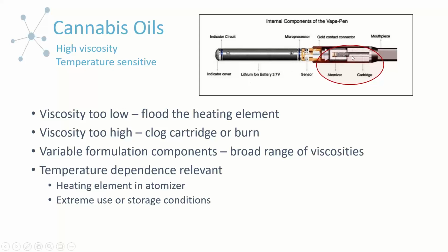Because if the viscosity is too low, then we can have flooding, essentially, of the heating element. If viscosity is too high, then you can have clogs in the cartridge, or rather than vaporization, you can have combustion or burning of the product on the heating element, which you would not want. Also, because these cannabis oils that come in the cartridges have a variety of formulations, everything from ratio of components to flavorings, you can have a very broad range of viscosity depending on the exact purpose of the product. And as I said, the temperature dependence is important to these particular customers, mainly because of the presence of the heating element in the atomizer. And then they've also talked to us about extreme use or storage conditions. So they're concerned with things that can happen if someone is using this in, say, Minnesota versus Texas.